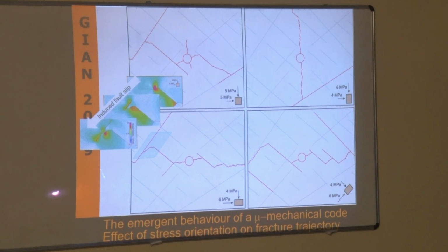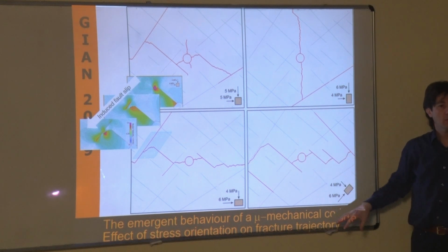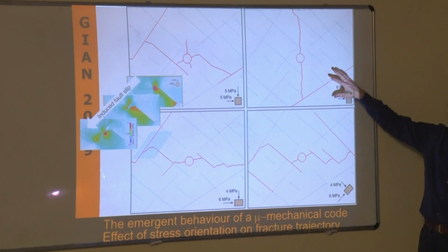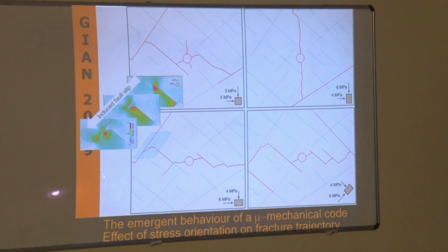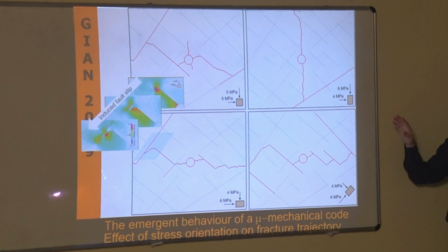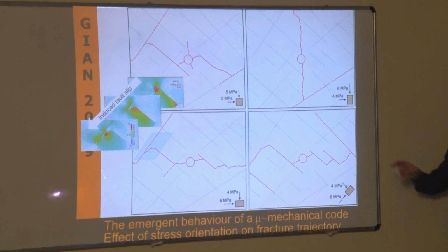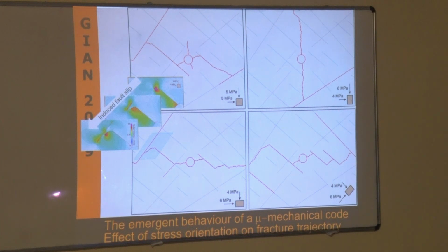So at the end, the fracture that develops really depends on the stress state. The path, the trajectory, depends on the boundary conditions applied to your model. Nothing changes between all these models but the stress state. That's it. The other interesting thing is that these fractures start interacting with pre-existing joints, pre-existing cracks, pre-existing fractures that were in the model. They were all the same.